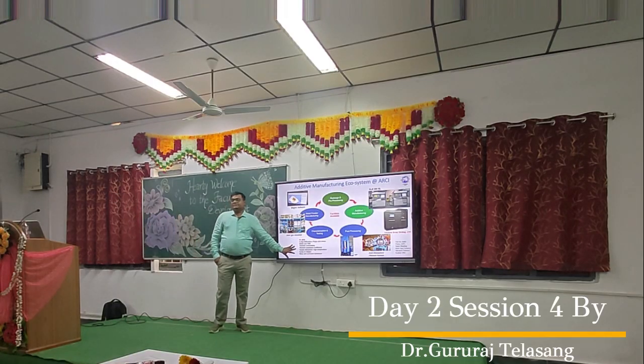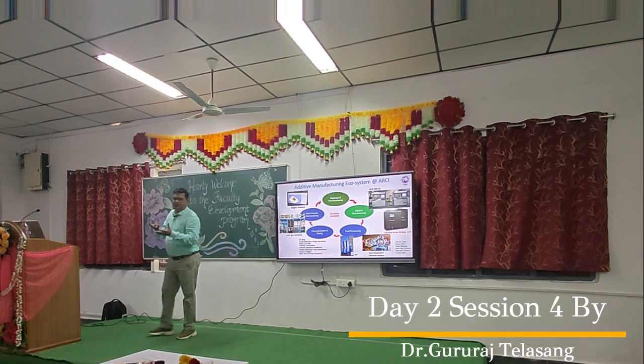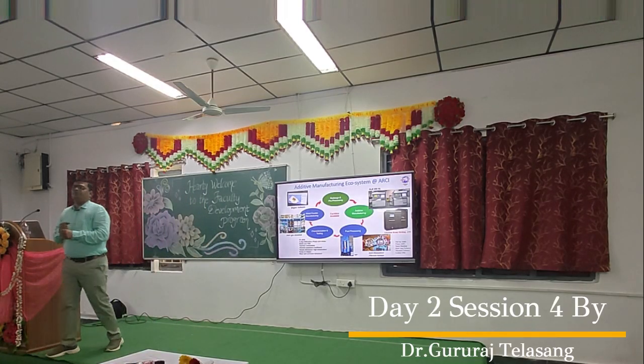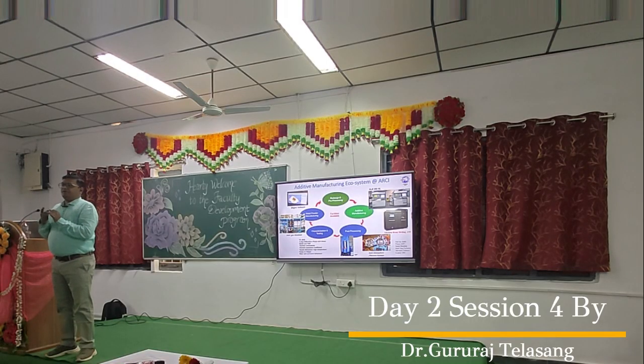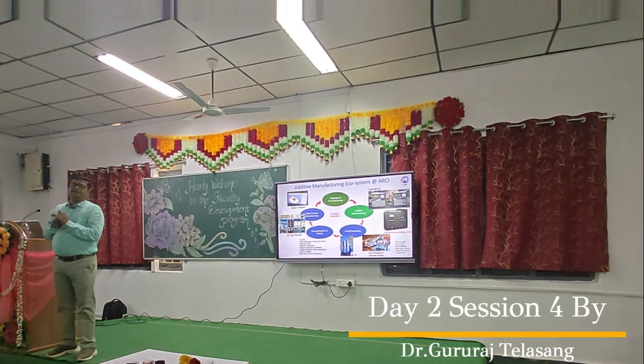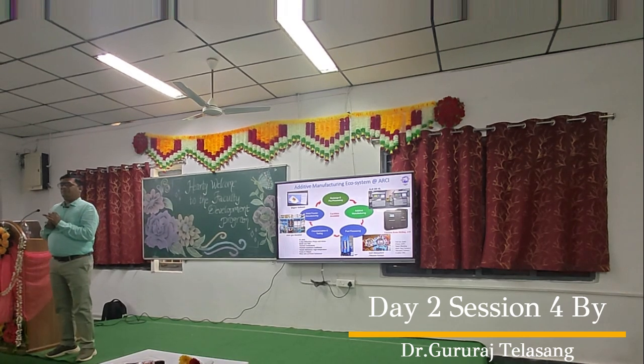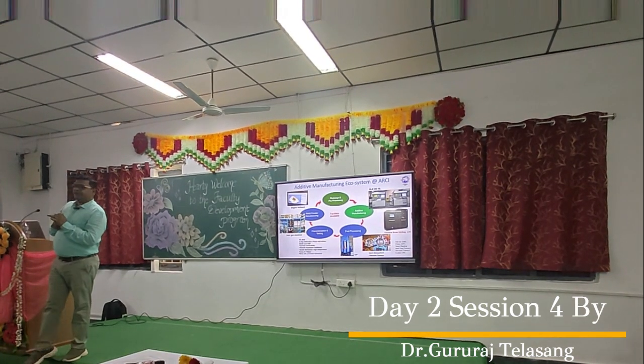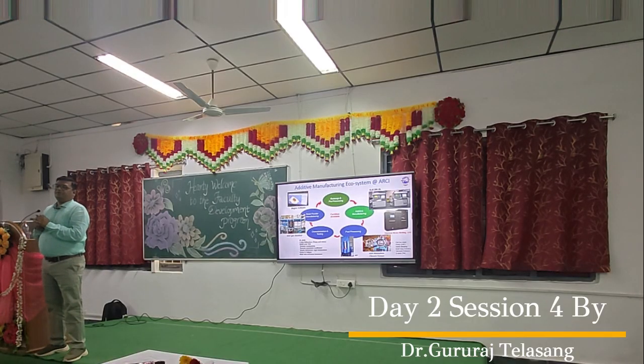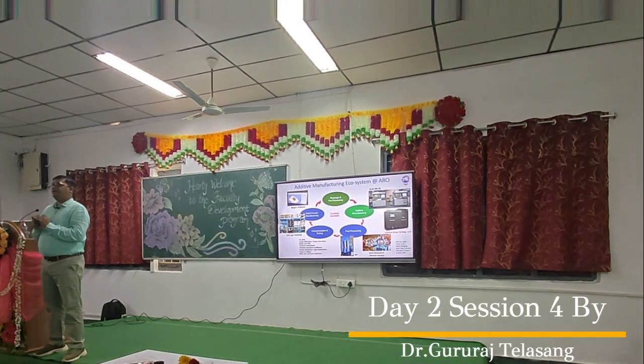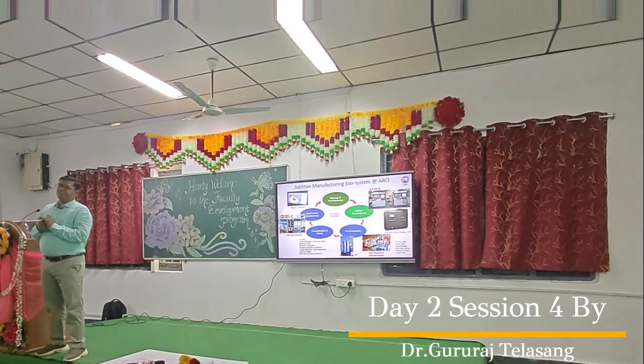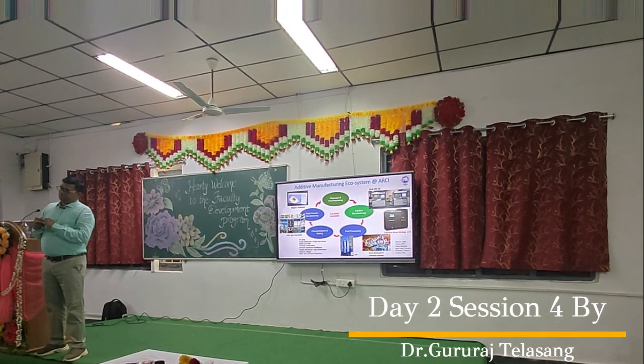So we have characterization. When I said metallurgical issues, we have to test them. You know the tensile test, you have the 3-point bend test. But there is something called XRD, X-ray diffraction, that is used for phase identification in metallurgical work. You know ferrite, martensite, right? Those are phases in iron, steel and all. When you go to other materials, you will find other phases. All those things will be identified by X-ray diffraction. And if you know the features of the material, you can see it by SEM.